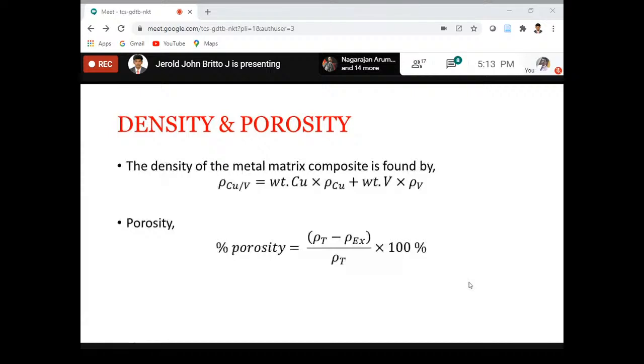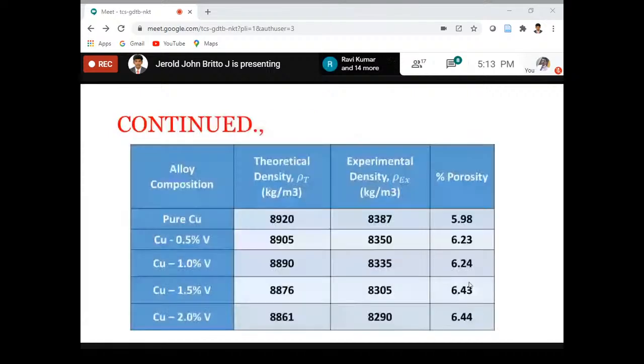Then I compared both the results: the theoretical density by rule of mixtures and the experimental density by Archimedes principle. By comparing both, I also found the porosity value. These are all the results. We can see that for pure copper the density is higher, and when you add the vanadium content, the density is getting reduced. As we know, compared to copper the density of vanadium is low. It is around 6 point something, but for copper it was 8.9. So that's why the density is getting reduced.